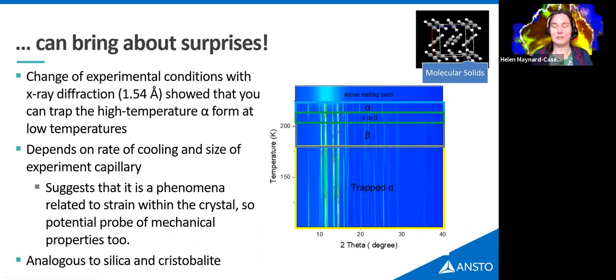And again, this is seen in earth minerals. So cristobalite, which is actually a high temperature form of silica, of quartz, that cools down too quickly. So a volcano erupts, it cools down too quickly, and it becomes metastably trapped at our room temperature. And it's one of those things that we can use, go out in the field and actually find and use it to say, hey, there's probably been a volcano around here. So we've suggested that this is a potential marker for Titan in that same context as well.